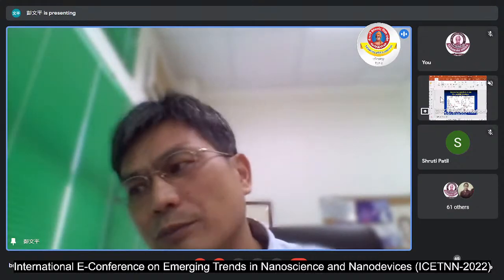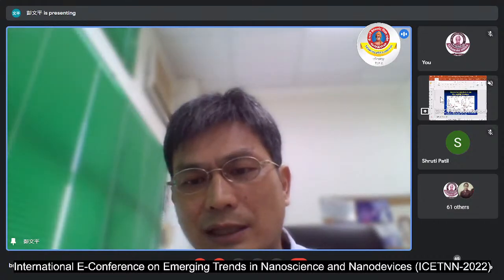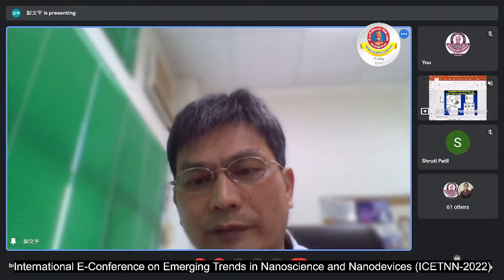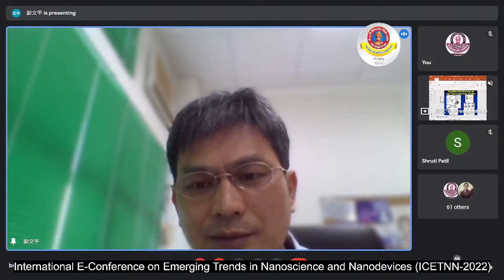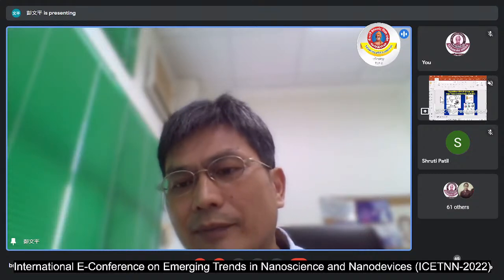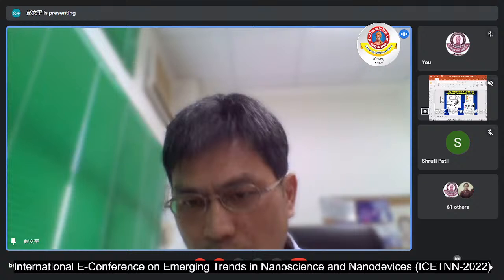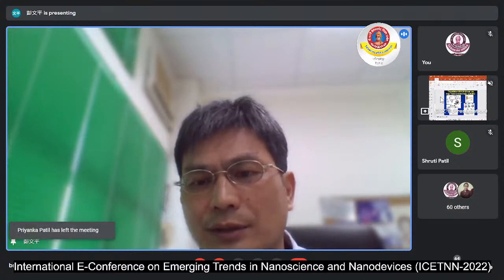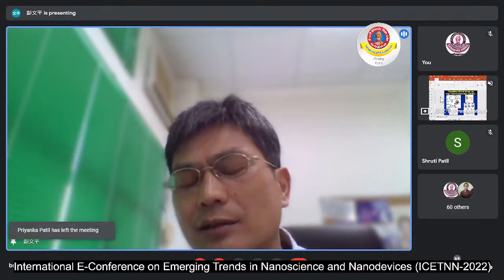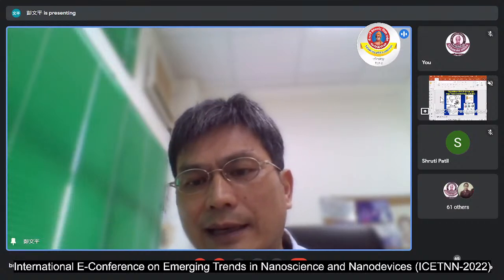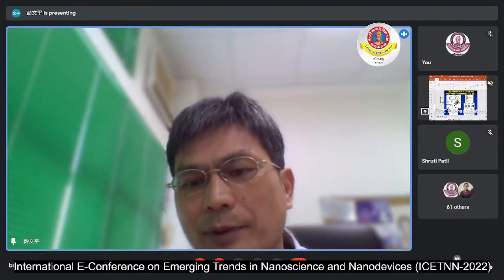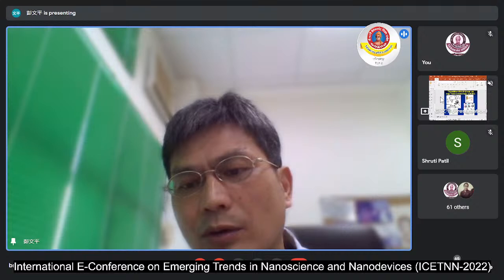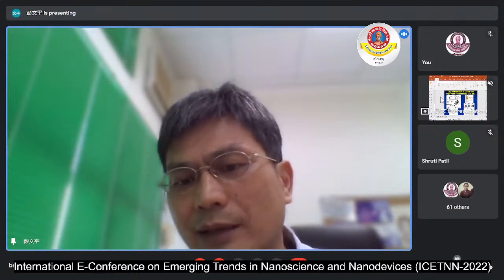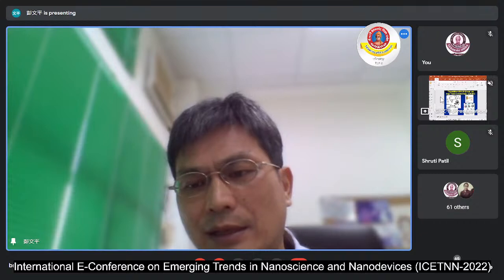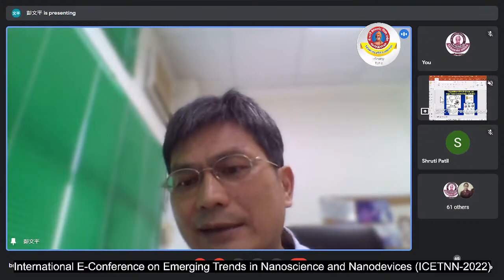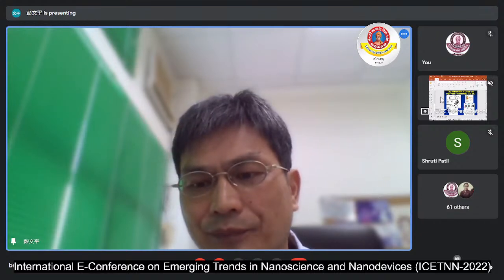Okay, I still have 4 minutes left, and let me introduce another technique. We developed our homemade instrument. Recently, we made progress in detection of IgM at a nanomolar concentration. This is our setup. We use a thermal linear ion trap as our mass analyzer, and we developed our own trap detector. It's very sensitive, with a noise of about 200 electrons. So that means we can detect 200 ions if you have those kinds of ions.